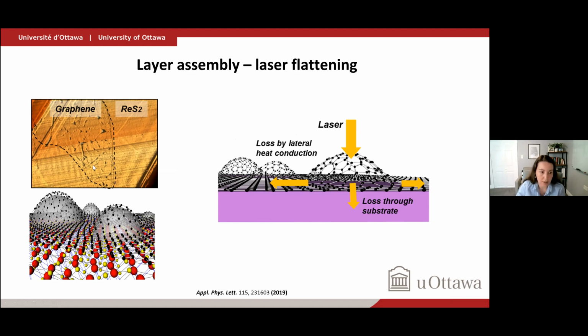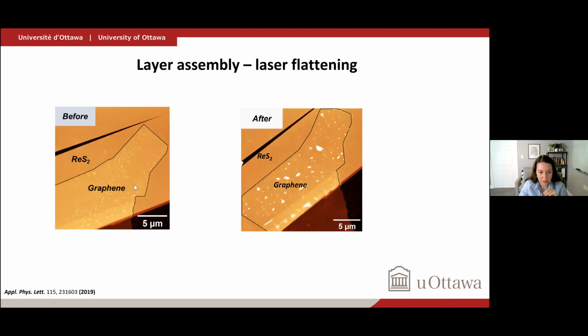And typically you put them in a furnace, you heat them up to a certain temperature to flatten them. But that may not be desirable in a complex circuit where you have different components that are heat sensitive. And so we came up with this idea where we have a laser that comes into a localized area and provides heat to the trapped gas in the bubble. And as a result of this heat, the contents of the bubble may escape through the sides and flatten the surface. And by doing that, not only is this a practical way to flatten the 2D materials, but we also learn, interestingly, a lot of things about the adhesion energy of these devices to their substrate. So that was a neat demonstration.